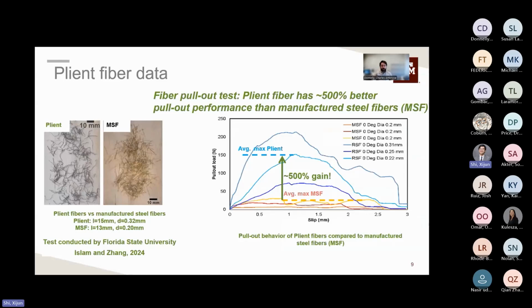So the first area is the pull-out strength. As I mentioned earlier with the surface characteristics, an important characteristic of any kind of fiber is how well the bond interface is between the fiber itself and the surrounding concrete. Tests were performed at Florida State University, comparing Plient fibers to traditional or standard manufactured steel fibers. Using a fiber pull-out test, it's been shown that the Plient fiber has 500% better pull-out performance compared to the manufactured steel fibers. This is critical because as a crack starts to form and open up, the fibers are holding the crack tight and improving the long-term durability of the crack itself. By having a higher pull-out performance, the Plient fibers are able to more effectively keep the crack closed and maintain the durability of the structure.